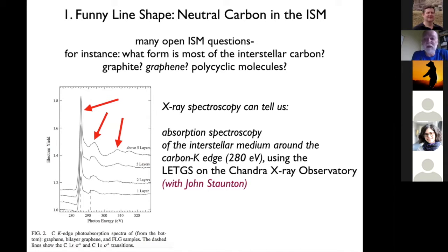And X-ray spectroscopy is a perfect tool for addressing this sort of question because, as you probably know, the energy levels in an ion or an atom respond to effects of binding and ionization to the tune of shifts of a few percent in transition energies in response to a single step in ionization. And that kind of thing we can nowadays actually resolve with X-ray spectrometers. So you see small shifts that are the response to chemical effects and ionization effects in the energies of edges and lines. And the other thing, of course, is that all the ionization stages have their K-shell spectra close together for the low Z elements.